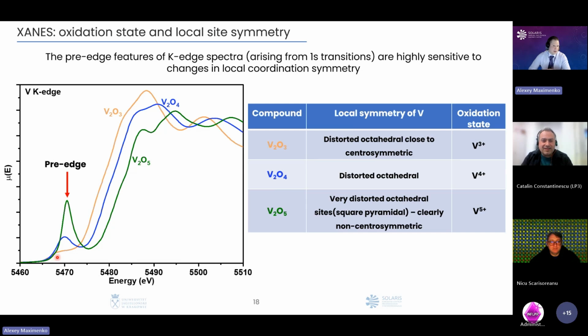Right. And in principle, yes, you can follow what is going on with the intensity. Again, you cannot take the intensity of this pre-edge peak for one unrelated compound and try to make a theory of a compound which you don't know just by analysis of the pre-edge peak. You need to know something about your material, you need to make some kind of hypothesis, and then based on it you can make the analysis. This is interesting for me, at least.